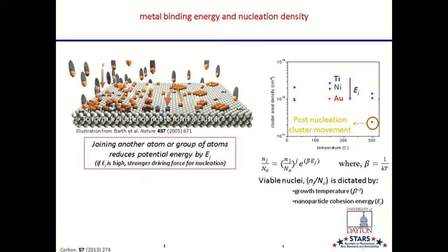So I'm showing here a mess of carbon nanotubes that we can turn into paper or yarn later. But we've attached different kinds of metal nanoparticles under identical conditions. We looked at gold, nickel, and titanium. Again, the conditions are the same for each of these processing experiments, but the morphologies of the particles are really different. You can see the gold really clearly, especially at high temperatures. You've got these big islands of gold, the white stuff on these dark nanoparticles.